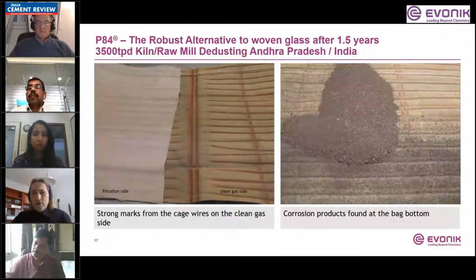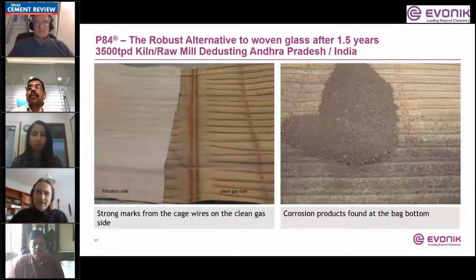And not only the corrosion of the cages, this was roughly a handful of corrosion products which we found inside the bag. Biggest share coming from corrosion of the clean gas plenum. And even though this does create some abrasion, a needle felt has also a non-woven wear layer on the clean gas side, on the cage side.